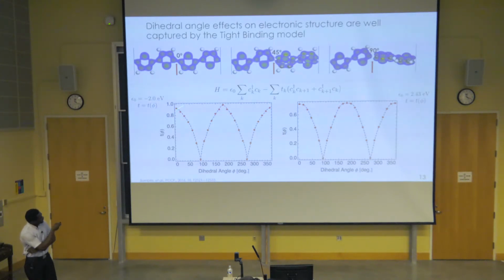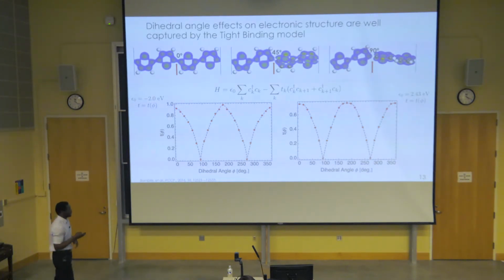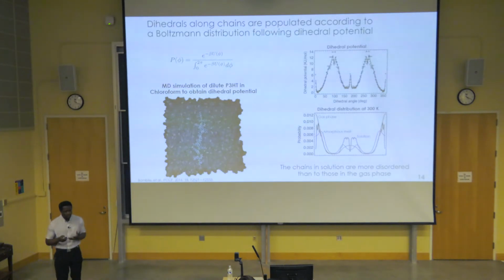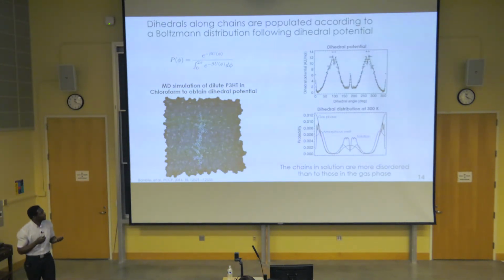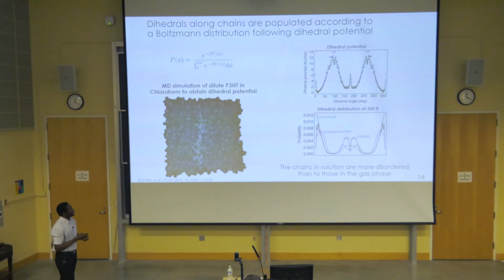The picture on the left here is this parameter as a function of dihedral angle as relevant for holes, for hole conduction, and on the right it will be the same for electrons. So having captured that, the second element we need is: what is the extent of dihedral disorder in a polythiophene chain in a given medium? And to do that, we turn to molecular dynamics simulations, and particularly we've done simulations for chains in solution,